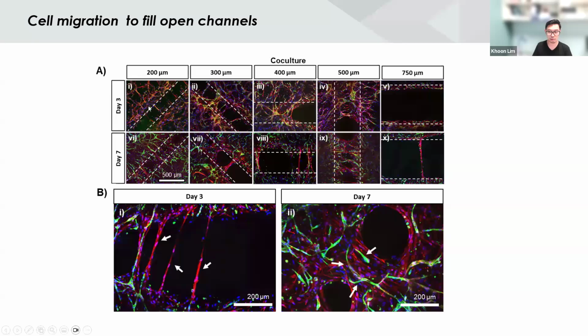So if the cells would come in, although you give them some pause, and then they are going to extend through all of these channels and fully pull and collapse the construct, then you're losing the whole point of printing this material from the very start, because it's just going to be a big hypoxic ball where the cells can no longer survive inside. What we found here is if you use 750 microns, you have less infill into this channel. So perhaps we really need to think about how we design the porosity within these materials and these constructs so that you don't lose the overall shape when vascularization is a key parameter to consider.